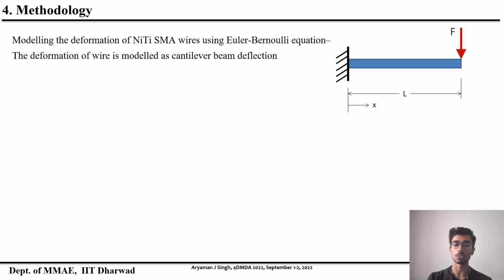Nitinol is a non-linear material which is comparatively more complex to model than a linear one. However, we have used the Euler-Bernoulli model applicable for linear materials only and compared it with a simulation resulting in the elastic range. By applying boundary conditions of zero displacement and zero bending on the fixed end, we have used the Euler-Bernoulli equation to model the 75 mm long and 1 mm thick SMA wire, similar to a cantilever beam.